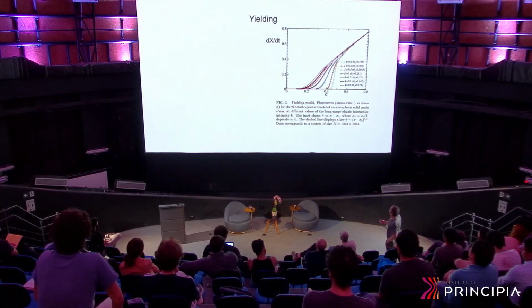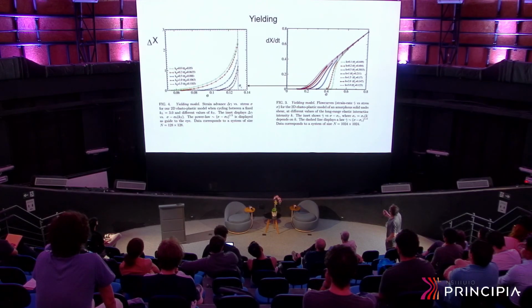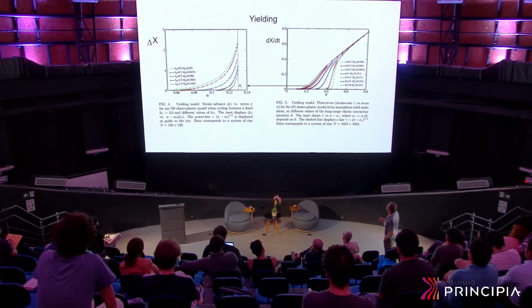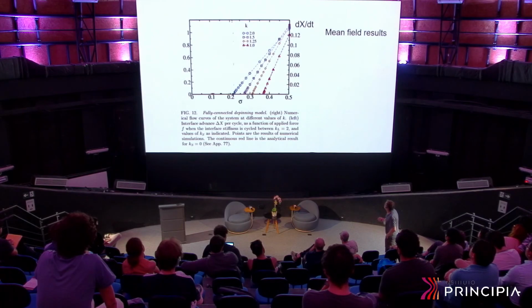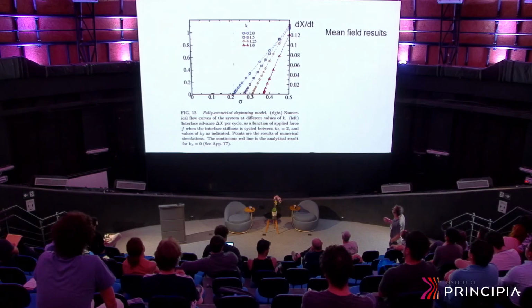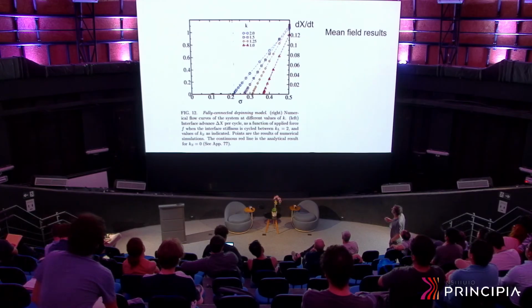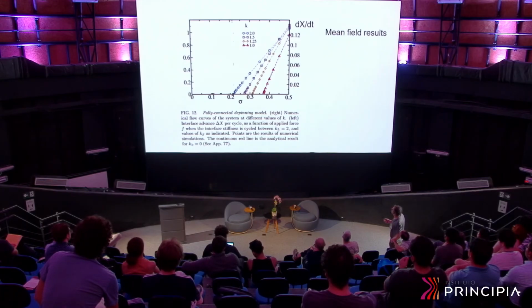Okay, the results for yielding are essentially the same. There are simply some qualitative differences in the form of the curves, which is a well-known behavior for people working in this kind of problem. And we also did this for the mean field results, which are interesting in the sense that we have some analytic results that can be used to interpret this. The flow curves in the case of mean field are known analytically to go to zero linearly, and this is in fact what we observe here.